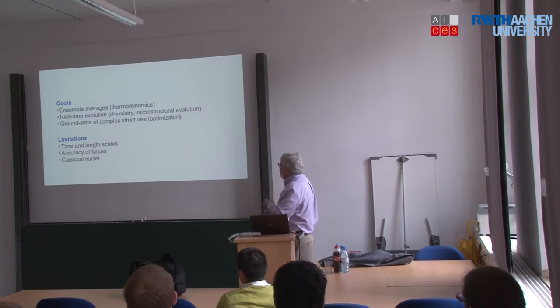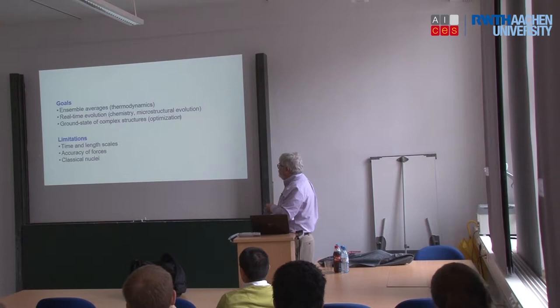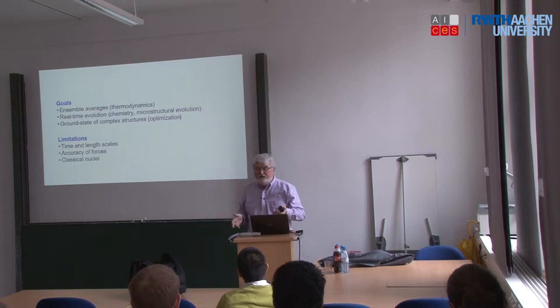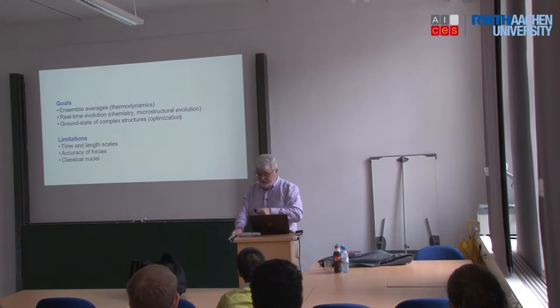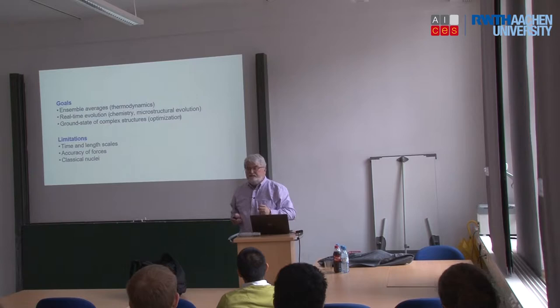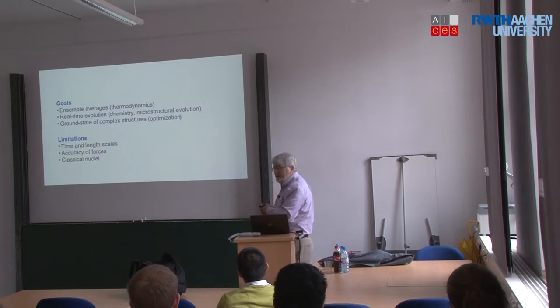What are the limitations? It has limitations in time scale and length scale. If you just think about the number of atoms involved, the separation of atoms is something like 3 angstroms. So if you're going to have a cluster of atoms, there's a certain number you can have. I should have worked out the numbers. But you're talking of a billion atoms being a fraction of a micron in size. A billion atoms is still a lot, even now, for simulations to do over an extended period of time. So that limits the size of the systems we can look at.